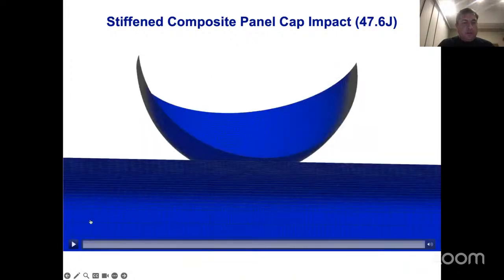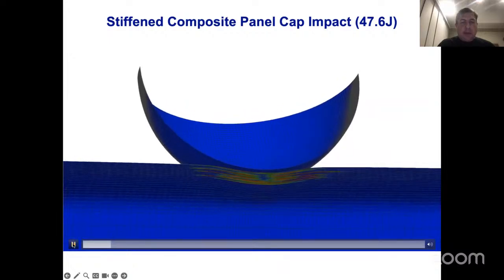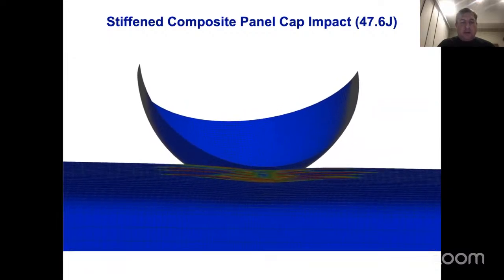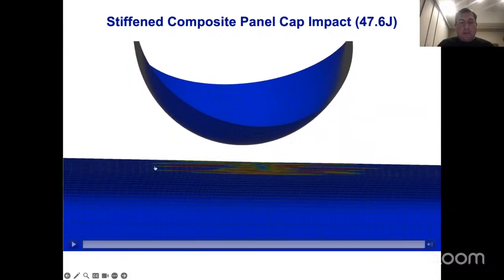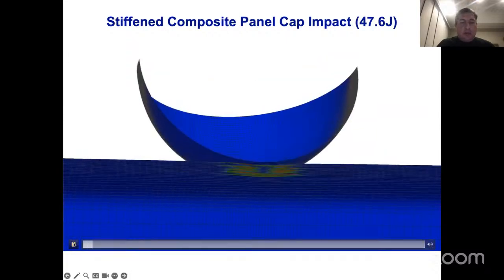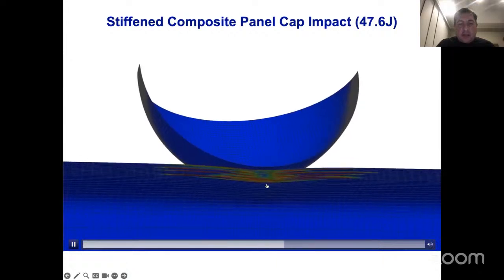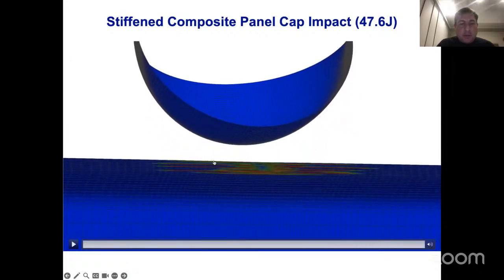So here's the view from the side. You can see the impactor that's descending on the stiffener. Let me play this again. And you see the onset and growth of delaminations between the different plies. In some cases, the extent of the delamination is quite large, but at some interfaces, you hardly see any.